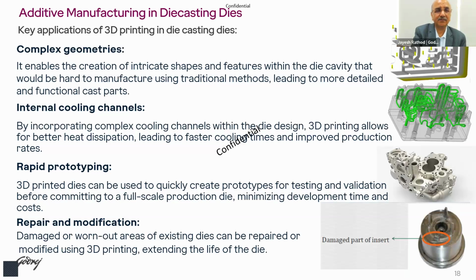Now if you look at the advantages of 3D printing or additive manufacturing in tool making, or in the total part making industry, the first thing is not only the cooling cycle, but the complex geometry. On the right hand side, the top one is an image of an insert where very thin projections need to be finally achieved. Those thin projections can be achieved by machining, using some EDM operation, which is again very costly, and a lot of material needs to be removed from very narrow grooves. So your metal cutting time increases because of that. If we go with 3D printing, where the material is built up, you get the advantage of very little machining, and a near net shape profile can be generated by using additive manufacturing.